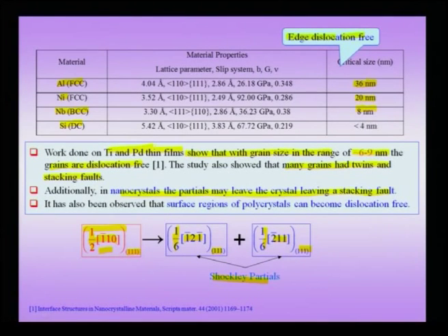And this has been observed experimentally in titanium and palladium crystals by Professor Ranganathan and his co-workers, and published in Scripta Materialia 2001. So in addition, of course, it is obvious based on the argument I have just made that even if you have a polycrystalline material or a single crystal material, the surface regions of the crystal may become dislocation free.